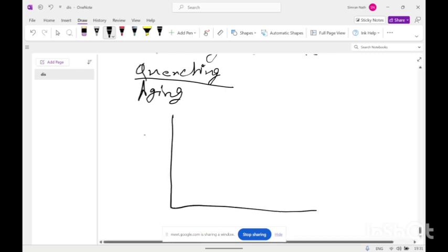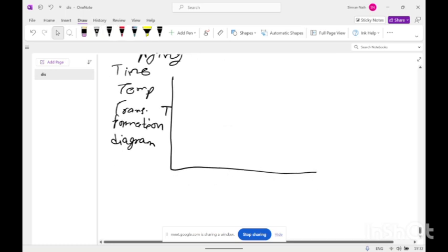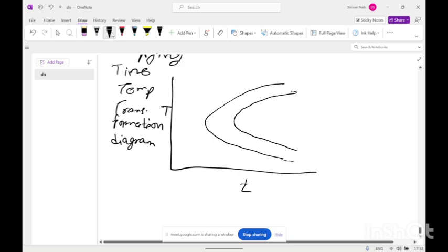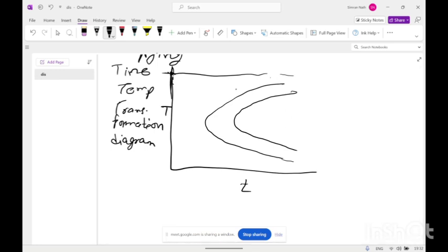If we see the time-temperature-transformation diagram, on the y-axis it is temperature and on the x-axis it is time. A C-type curve is formed during the cooling of any liquid. This is the single phase region temperature. If the cooling rate is high, the first curve shows the starting of the nucleation of the secondary phase, like 1%, and this is 100%, meaning start and finish.